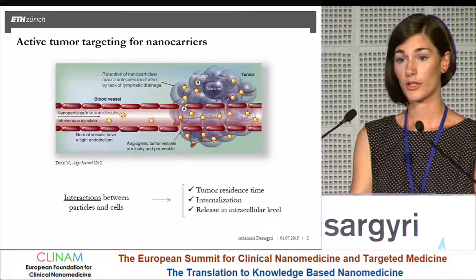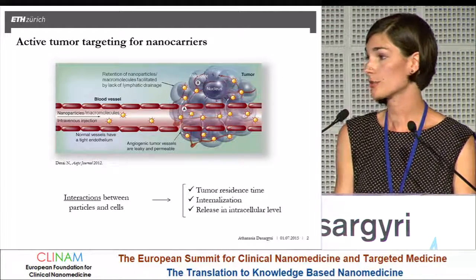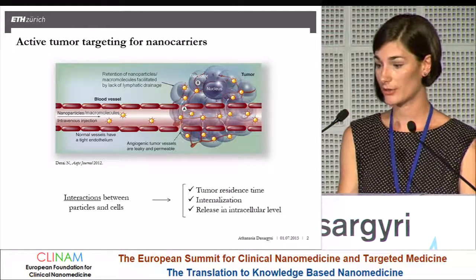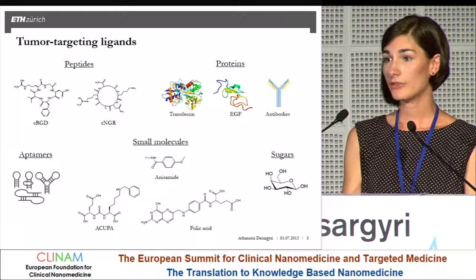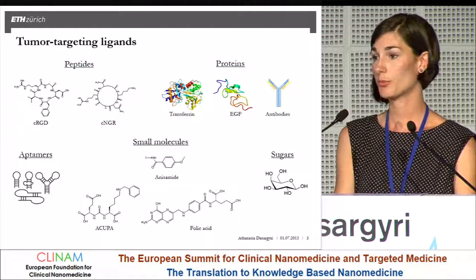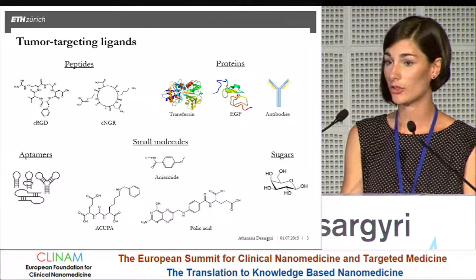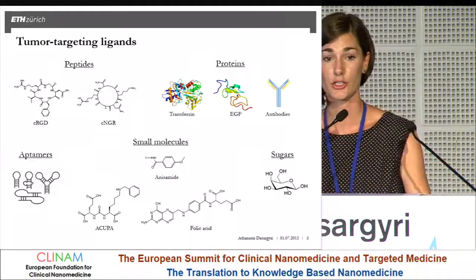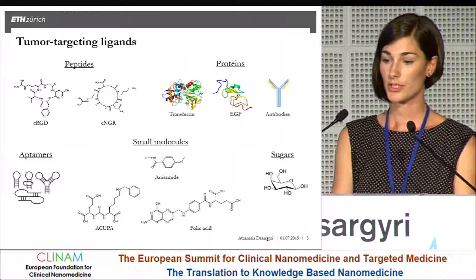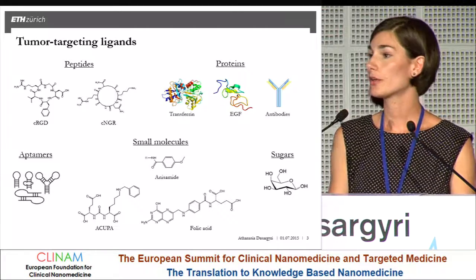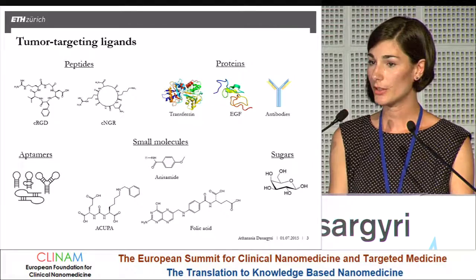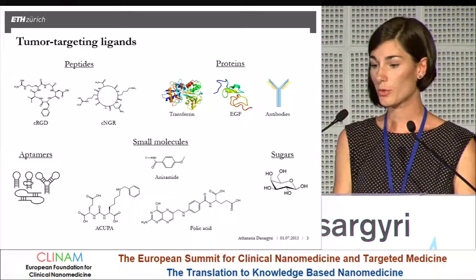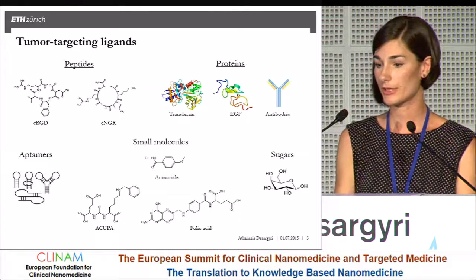Active tumor targeting with nanoparticles aims at increasing the interactions between the particles and the tumor cells after the particles have extravasated at the tumor site. Among the different tumor targeting ligands used in preclinical research, small molecules have recently attracted much attention because of advantages including lower risk of immunogenicity, higher stability compared to large biologic molecules, and ease of incorporation on the nanoparticle surface by simple chemistry.